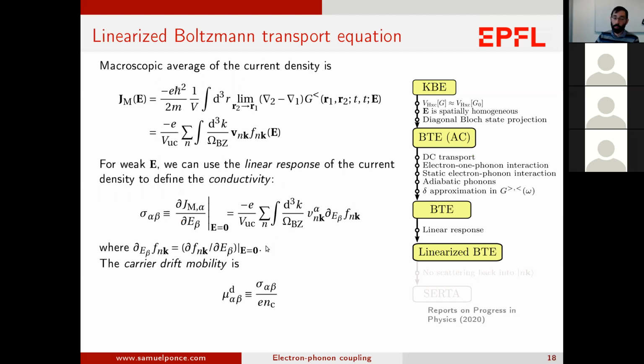Now, experimentally, they don't really like to report the conductivity because that depends on the amount of carrier you have. So the more carrier you have, the bigger the conductivity. And therefore, typically people prefer to refer to the carrier drift mobility, which is the ratio of the conductivity by the number of carrier that you have. And this is more intrinsic. It is really an intrinsic property of the material.